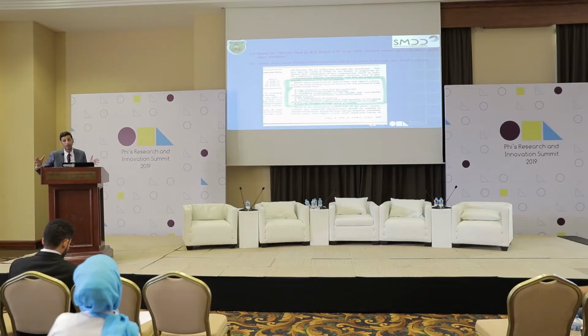In applying membrane distillation, I will just go through the concepts more precisely in the next few slides. But I read this patent and this paper to identify the membrane requirements to achieve this process. The membrane should have a high resistance to heat flow by conduction, so you don't lose a lot of heat, because it's your driving force. The membrane should not have an excessive thickness, because the thicker the membrane, the higher the resistance and the lower your flux. Flux means the water production rate.